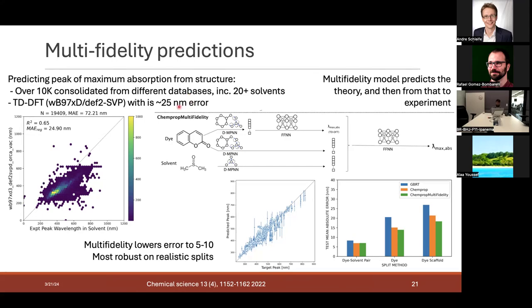It's not amazing, but this workhorse simulation technique, time-dependent density functional theory, has about 25, 30 nanometer error. And for folks that operate in other parts of science, that's about one color in the rainbow. So DFT is about one color in the rainbow wrong. This is the correlation in our 20,000 points that we had at some point between what experiments say and what DFT says. So, it's okay. It's linear. It has some bias. The slope is not 1, but it's not trivial.